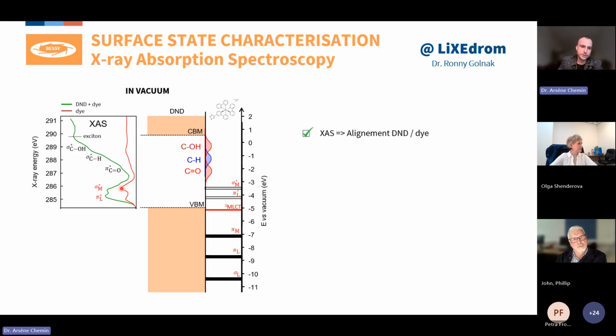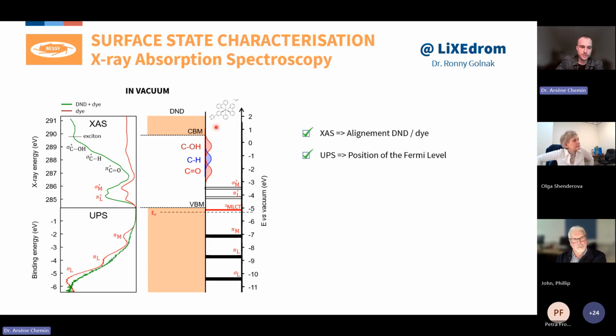And you can also see those two states absorbing a lot, which actually correspond to the unoccupied orbitals of the dye, so of the ruthenium dye at the surface of the diamond. For the occupied state, we cannot perform X-ray absorption spectroscopy. What we do is UPS, so photoemission spectroscopy.